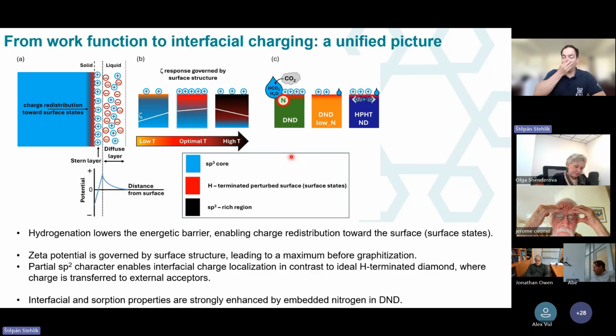So then we constructed this unified picture, let's say. It has 3 panels, and in panel A, we simply wanted to show that the formation of the positive zeta potential is primarily because of the hydrogenation, as it indeed lowers the energetic barriers and enables the charge redistribution towards the surface states. Okay, and so this is the general mechanism which we think is quite plausible.